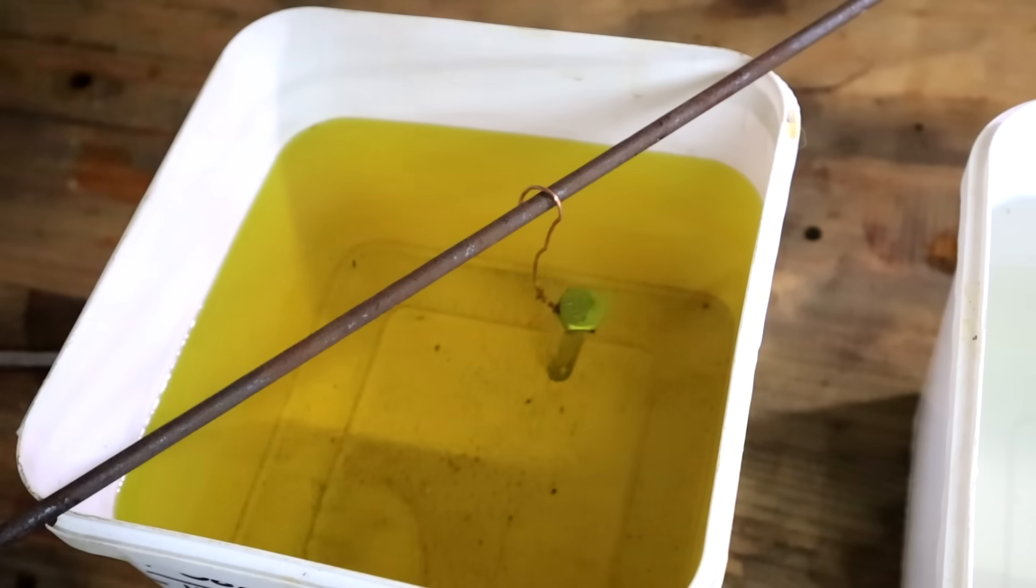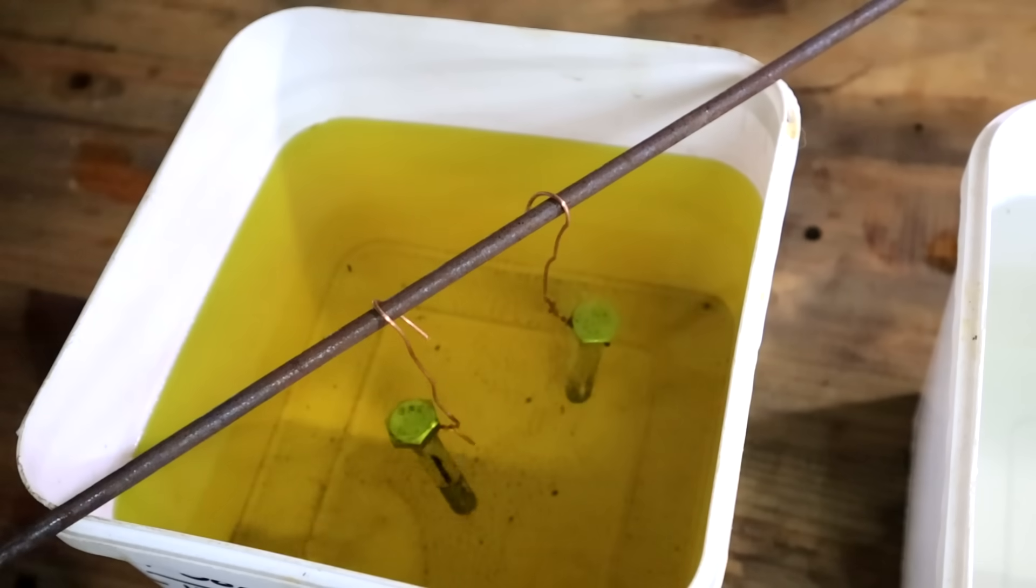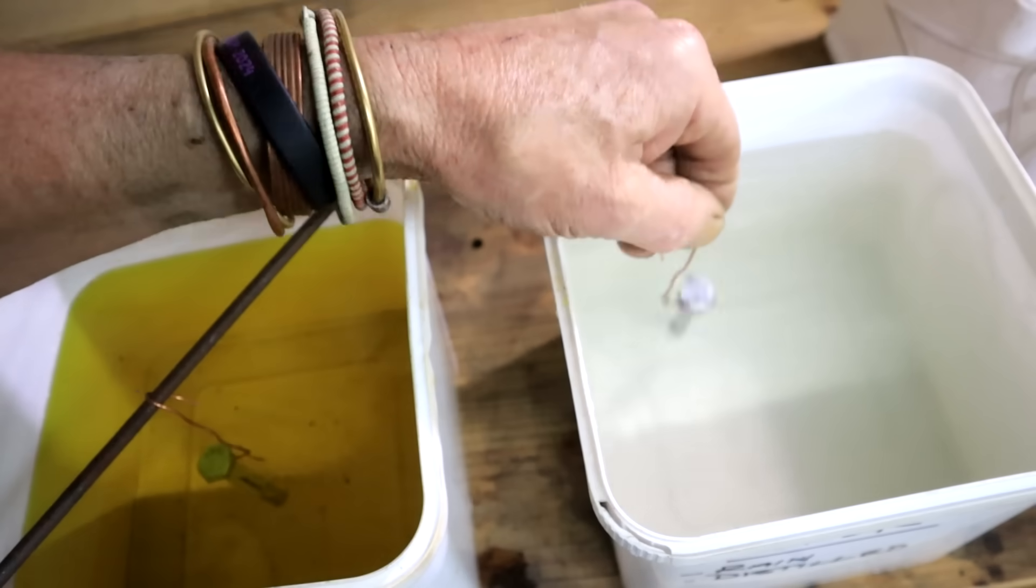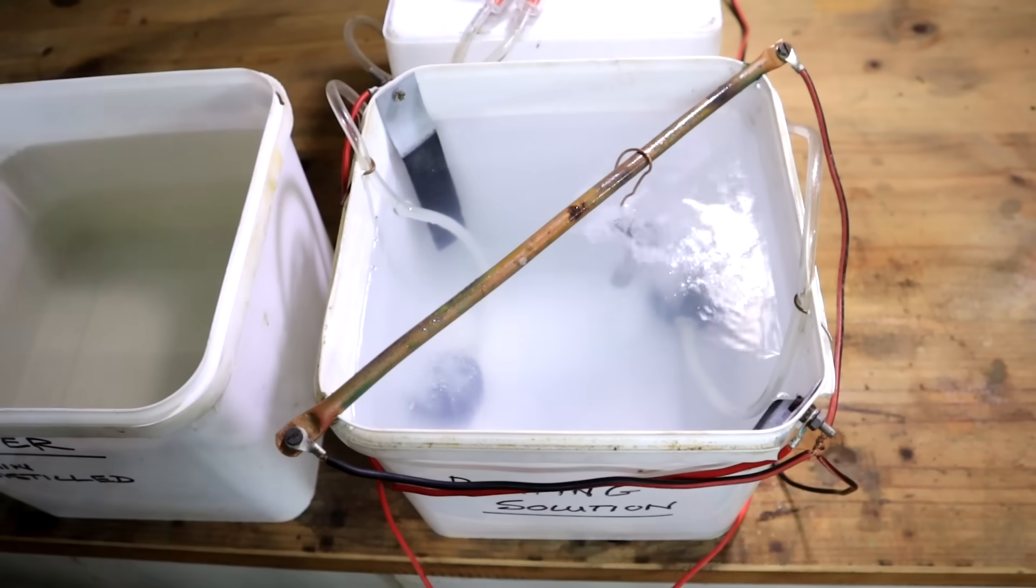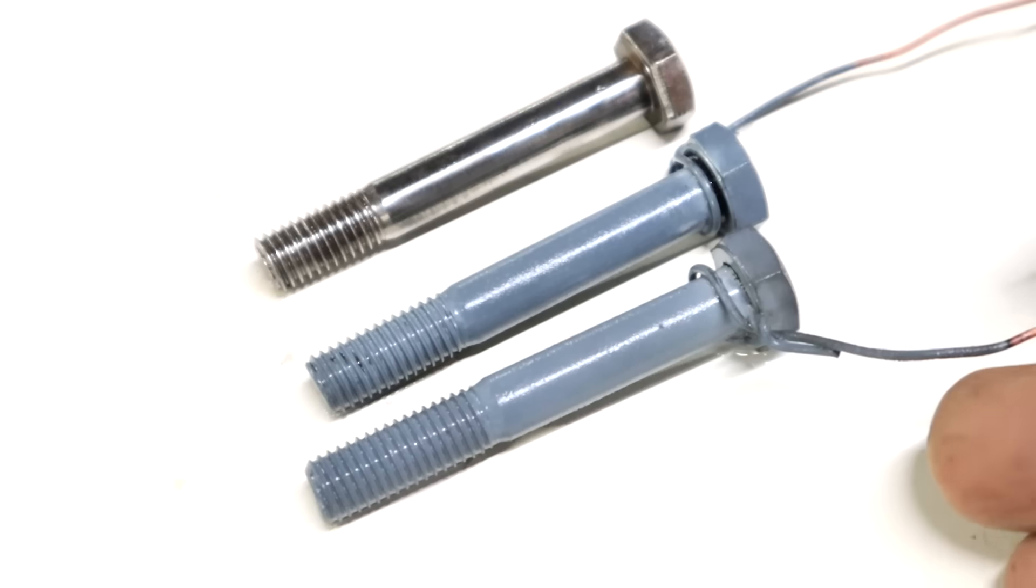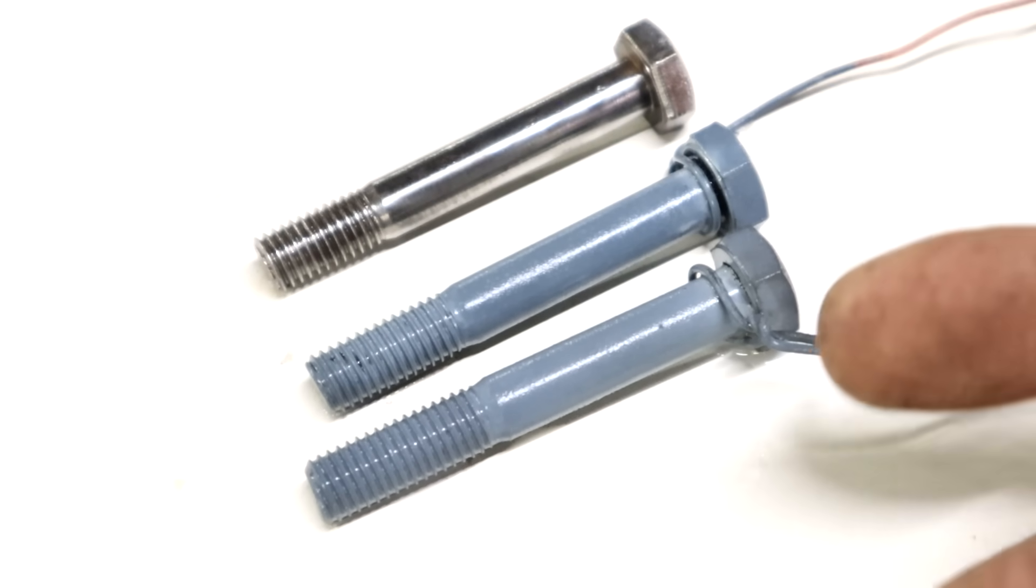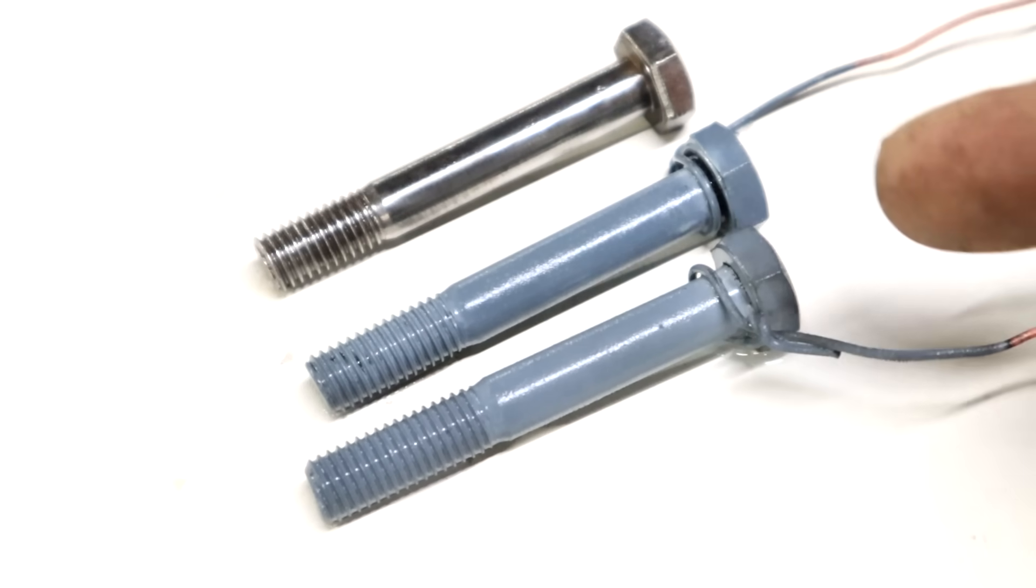Dip them in hydrochloric acid until there are no bubbles. Let's rinse in my fresh water. And into the plating solution you go. And you. Bubble, bubble, toil and trouble, we are plating. 15 minutes in the plating solution. And we've got some good zinc plating going here. Here on the back is an unplated bolt for reference.